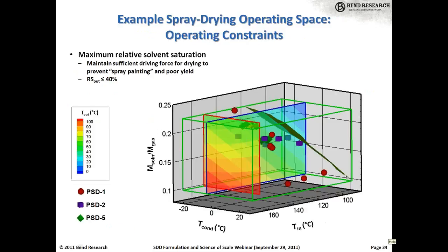And again, you can insert a plane, kind of an operating constraint plane, where you don't want to operate the dryer too wet, or you lose your driving force for drying and will begin to spray paint and lose yield. So you don't want to operate in this cold, wet region in the back corner of the cube.